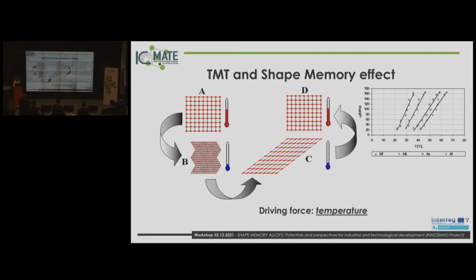The martensitic state at low temperature can be deformed by applying a stress, and then we have the detwinned martensite, the deformed state of the material. And then when we increase the temperature, the material recovers its initial shape by the transition from the martensitic state to the austenitic state.